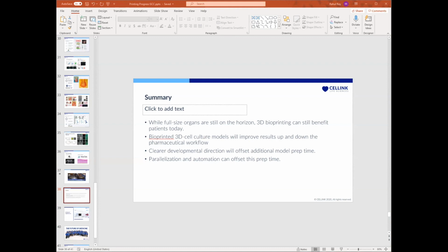So I guess it depends on the bioprinting technology. Of course, if we're talking about extrusion, which is arguably the most common one, shear is certainly a known issue for extrusion printers. And so allowing yourself to use a larger nozzle diameter, as large as possible for your particular application, can certainly help.